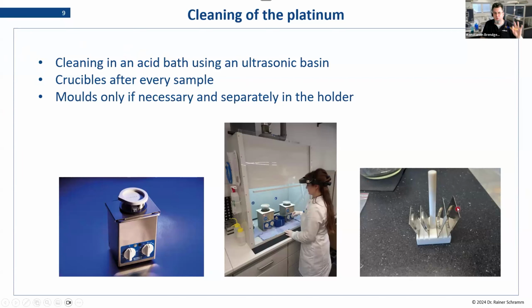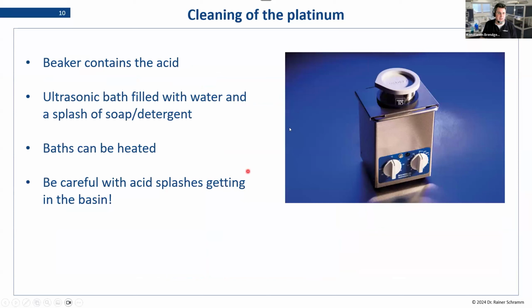Again, we want to be very careful handling the platinum molds. So for cleaning, we always use this little holder. We put them in, sort of like in a washing machine, and we never put them together with the crucibles. They always get their own separate beaker so that we avoid scratching from the parts touching and being exposed to the ultrasonic waves. The setup in our laboratory is similar to the picture here. We have a 600 milliliter beaker. That's where the acid goes in, and that's where your platinum goes in. This is then put into an ultrasonic bath, and the basin is filled with just plain water, and we always add a little drop of soap or detergent.